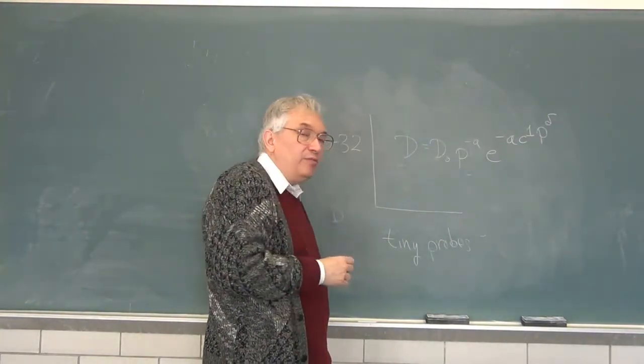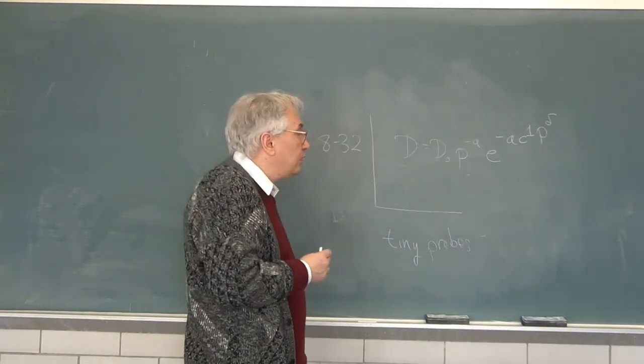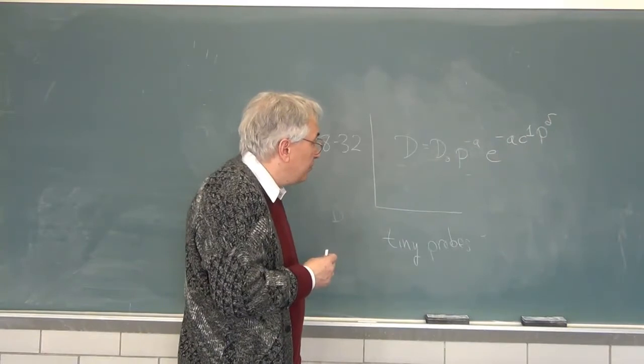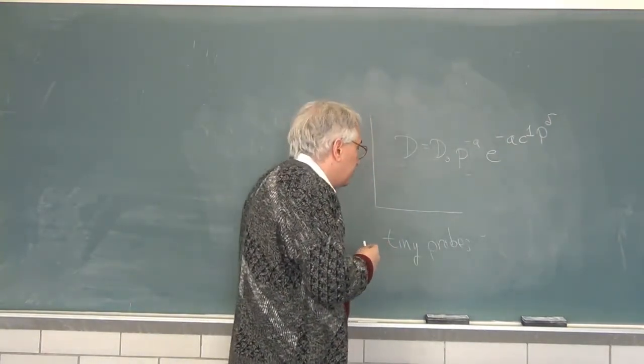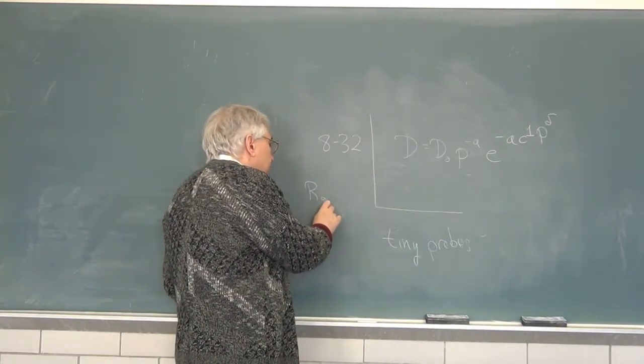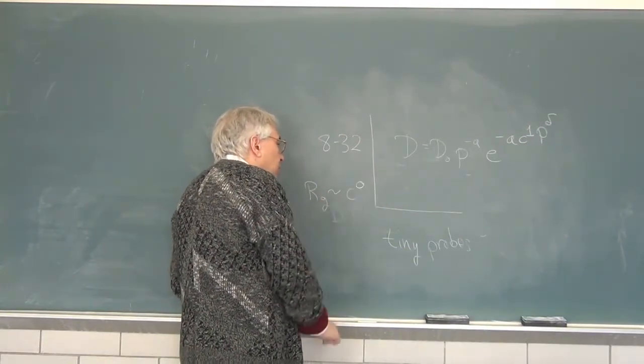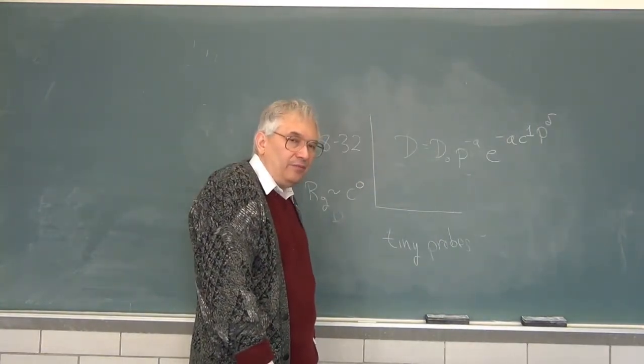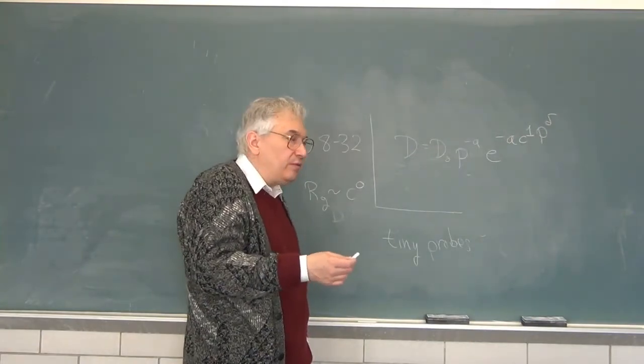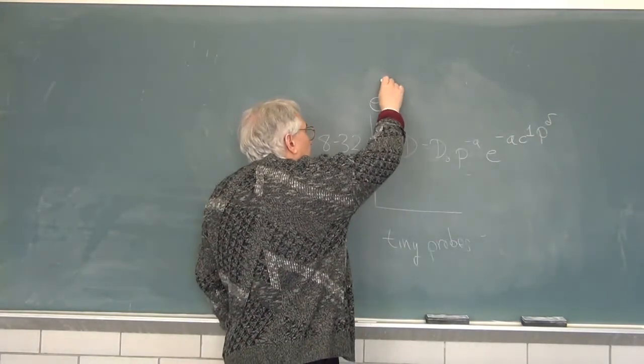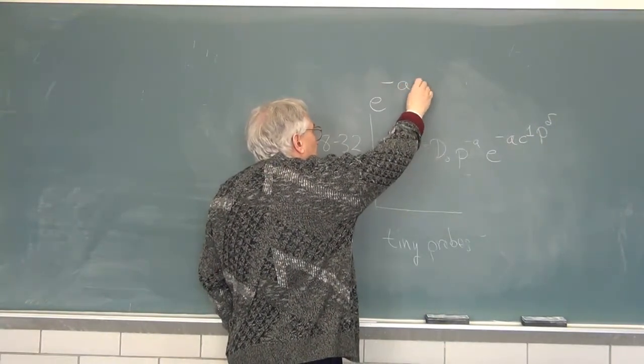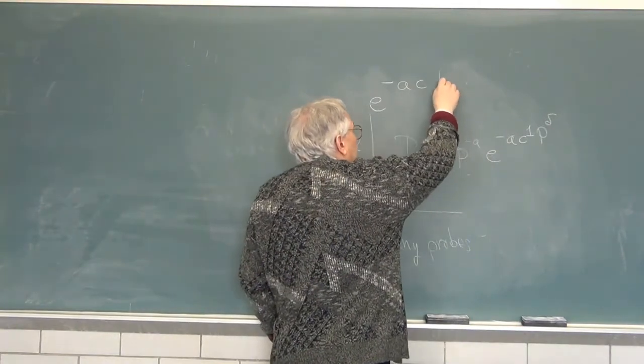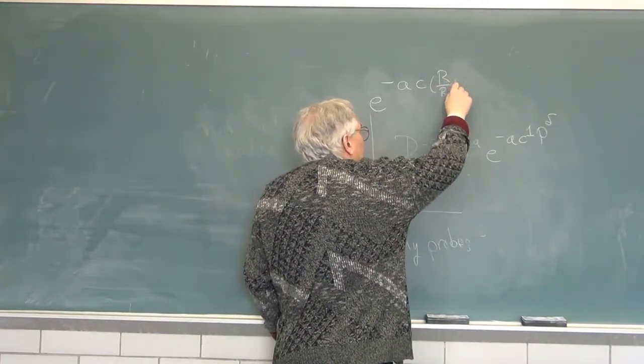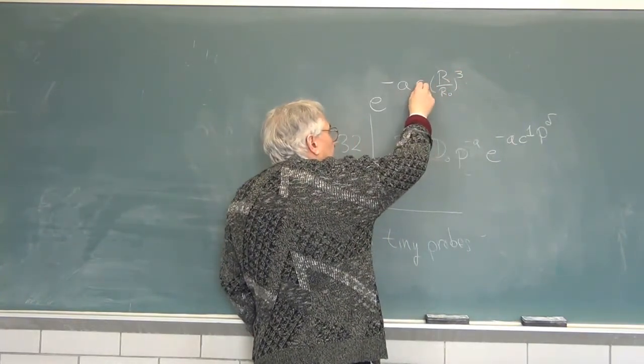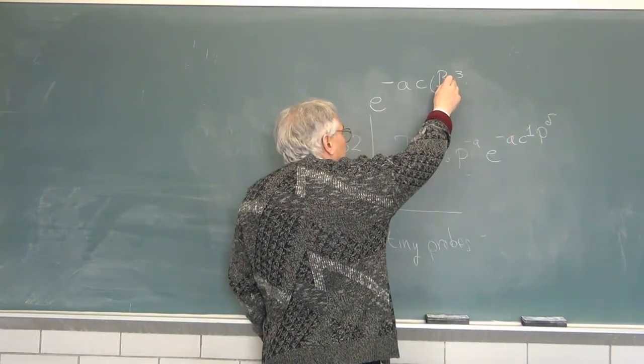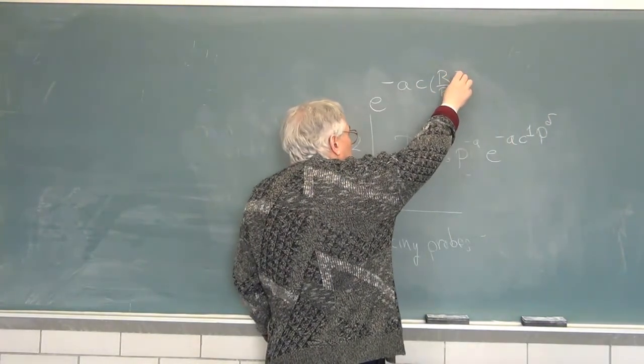And you can judge for yourself, but the agreement of fits and data do not look too bad. There is, however, one other little bit. These are very low molecular weight probes, a few kilodaltons, and one expects for very small probes that the probe radius is more or less independent of concentration. If you think back to the chapter on dielectric relaxation, we made the point that the concentration dependence could be written as c to the first, R radius over radius at zero concentration cubed, and the deviation from a simple exponential was entirely covered by the contraction of the chains to the cubed power.